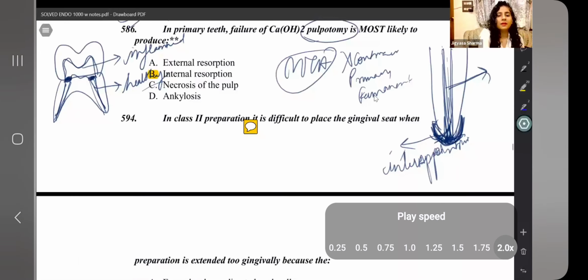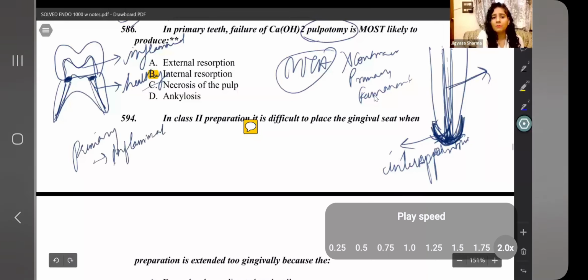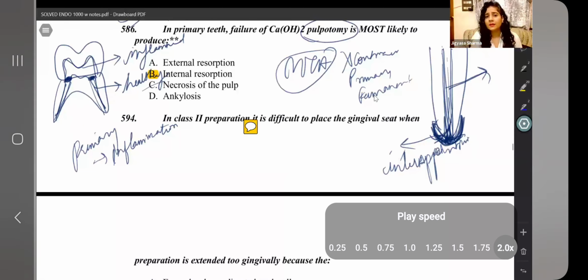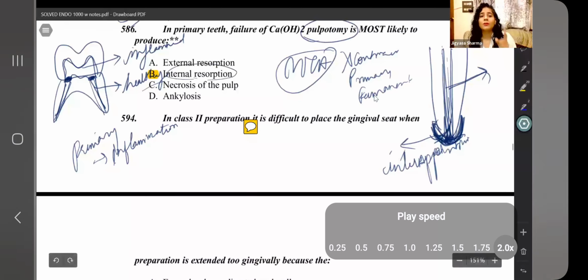So calcium hydroxide is contraindicated with primary teeth wherever you see that there is inflammation. Wherever you find that pulp was inflamed or possibly inflamed, calcium hydroxide, when you put it on the pulp, will lead to internal resorption. So answer is simple. When you put calcium hydroxide as pulpotomy calcific barrier, what is the most likely response? The failure, it would be because of internal resorption. So that's a fact. When you put calcium hydroxide on primary pulp, where there is a possible indication of inflammation, then the pulp shows an unexplained reaction of internal resorption. It is unexplained because the mechanism is not known. But it is a finding, and that's why you have to learn this. That it is a contraindication with calcium hydroxide pulpotomy. And pulpotomy is only done when the coronal part was inflamed. That means the inflammatory component is there, so you can't use it.